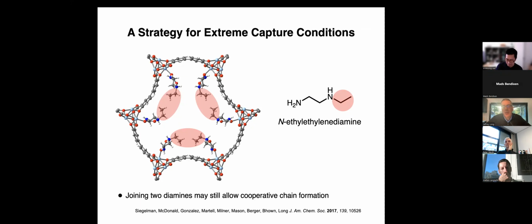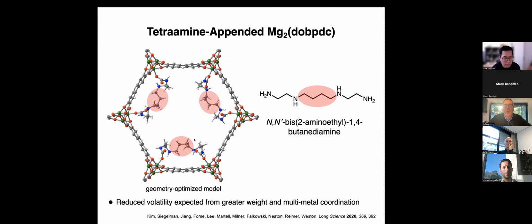And so one issue is if you're working at very extreme conditions, very high temperatures, then from some of these adsorbents, you might start to volatilize the diamines. And you would gradually lose capacity as you would adsorb and desorb CO2 at these very high temperatures. And so from looking at crystal structures, we had the idea that we might be able to connect a pair of diamines in the adsorbent and create a tetraamine that would still allow this cooperative chain forming mechanism. And so here's just an example of such a tetraamine that we tried.